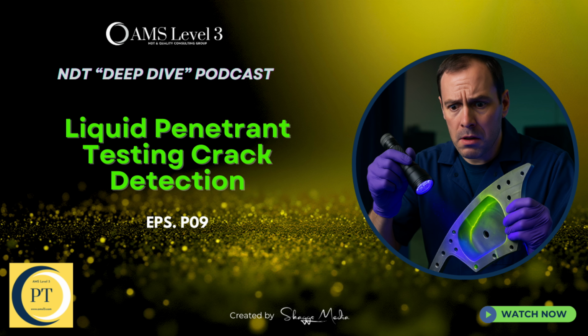But there's a really important note for any wet developers, whether they're water-based or solvent-based. The developing action, the bleed out, doesn't really kick off until all the liquid carrier, the water or the solvent, has completely evaporated and the surface is dry. Oh, interesting. So you apply it wet, but it only works once it's dry. That's right. And there's another timing issue here, too.